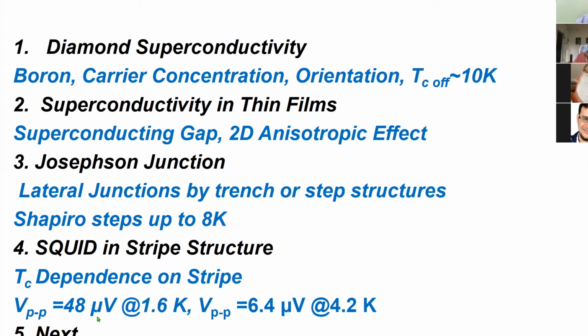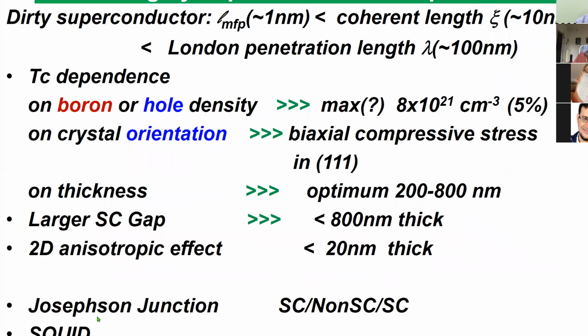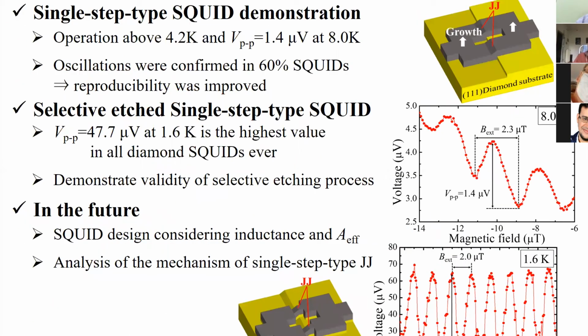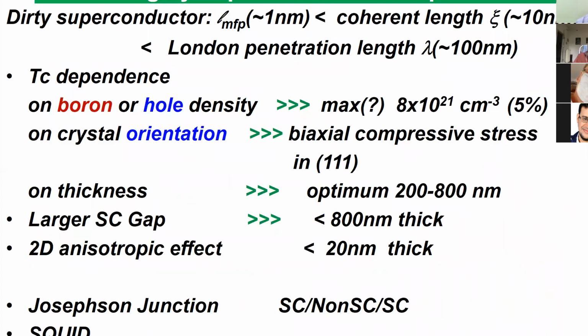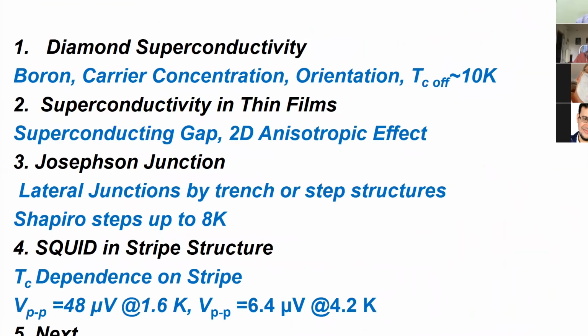That means here, from here to here, the peak to peak is about 40 or 50 microvolts. This is at relatively low temperatures, but it's okay. Compared with other SQUIDs and commercially available ones, this value is of course much higher than others, but now we are approaching this using narrow stripe patterns.